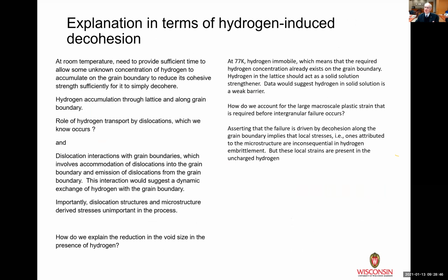So I just mentioned that the grain boundary could fail, and that's been one of the classic mechanisms that's been put out there. It's the hydrogen-induced decohesion mechanism. What it says is that hydrogen goes on the grain boundary, reduces the boundary cohesive strength enough that it just fails. Any plasticity that happens in the material is totally irrelevant to the failure. There's nothing to do with it. Is that right? We also know that dislocations transport hydrogen. There's some very elegant experiments that have been done that show that. So if hydrogen is transported by the movement of dislocations, and we need to put enough hydrogen on the grain boundary to get decohesion-induced failure, is it right for us to say that plasticity has no role in hydrogen-induced decohesion of a boundary? I'd say, no, you need to pump more and more hydrogen on the boundary, so that transport is important.